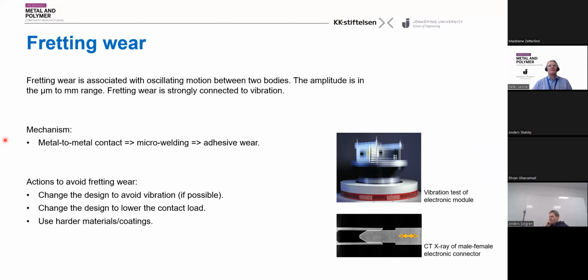The mechanism could be that you have micro welding, which will lead to adhesive wear. And then you can say, okay, how do we avoid this type of wear? The best thing is, of course, if you can change your design so you don't have vibrations where you have your contact, but it is easier to say than to solve in reality. Then again, you can lower your contact load, so you have lower mechanical force, or you can increase the hardness of the materials in the contact bodies. On the lower picture to the right, you will see an X-ray photo of an electronic contact, a male-female contact. And you can imagine if this is vibrating, that it's easy to have damages just in the contact area.